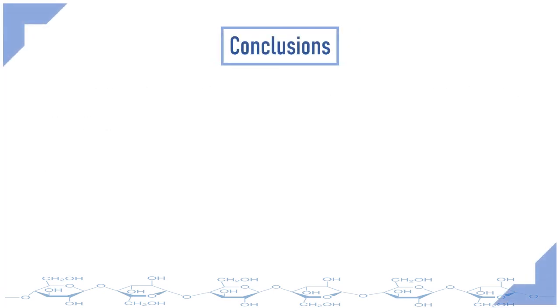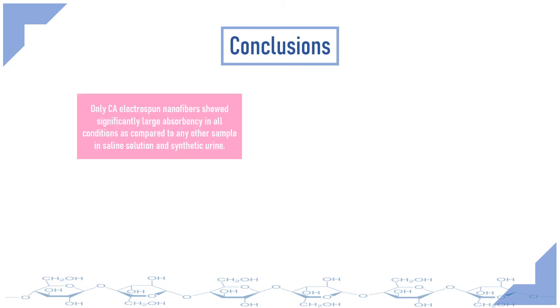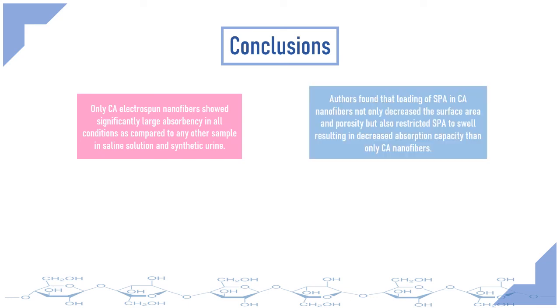Finally, we can talk about the conclusions. Only CA electrospun nanofibers show significantly large absorbency in all conditions, as compared to any other sample in saline solution and synthetic urine. Authors found that loading of SPA in CA nanofibers not only decreased the surface area and porosity, but also restricted SPA to swell, resulting in decreased absorption capacity compared to only CA nanofibers.